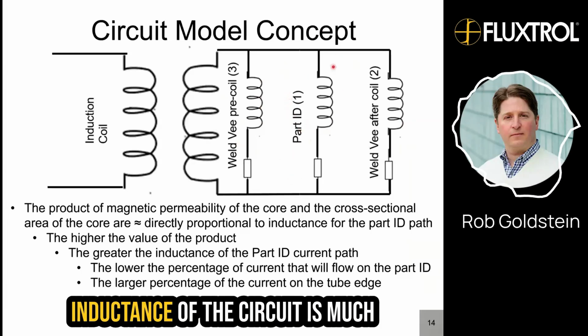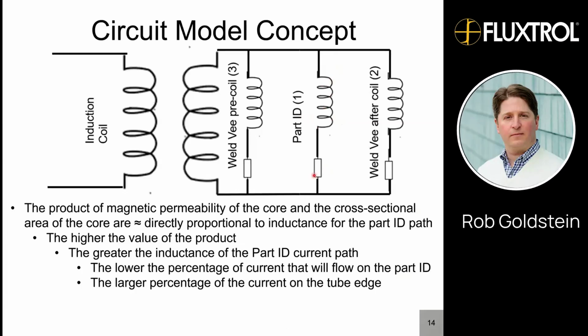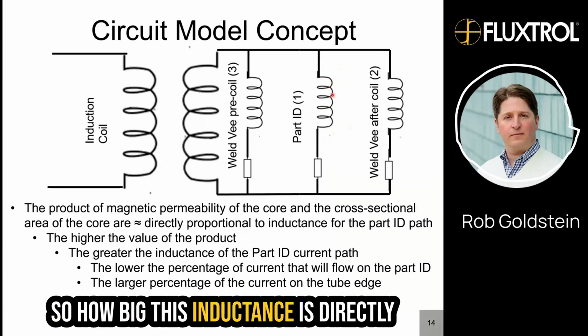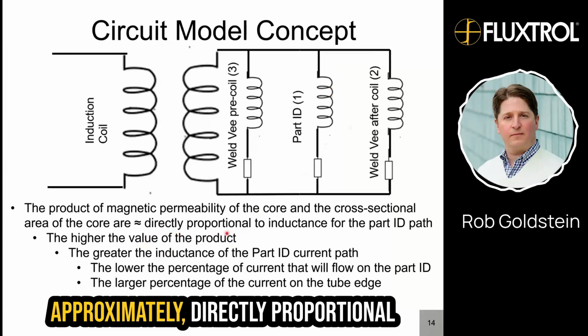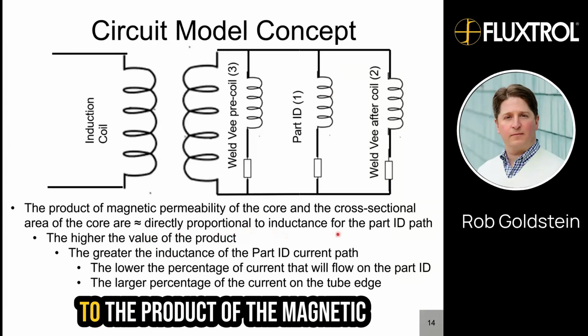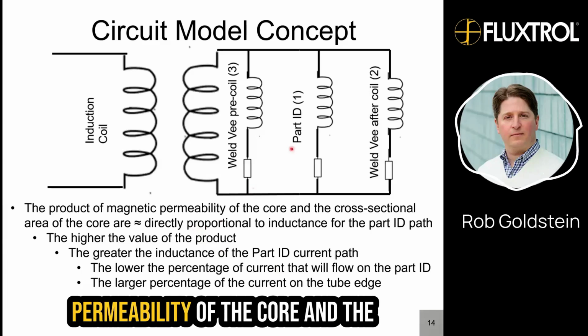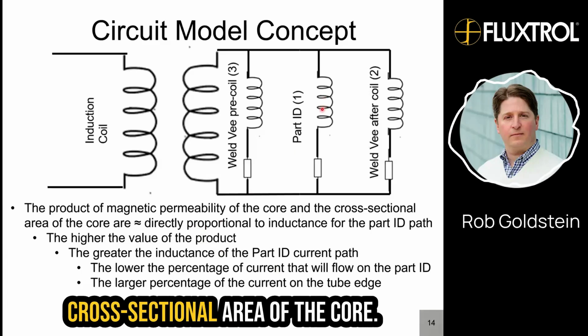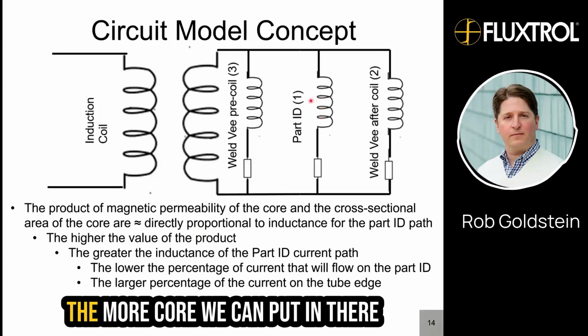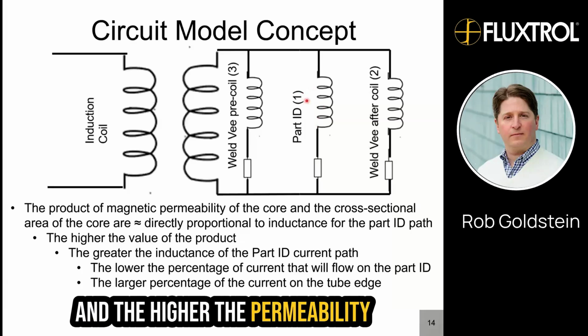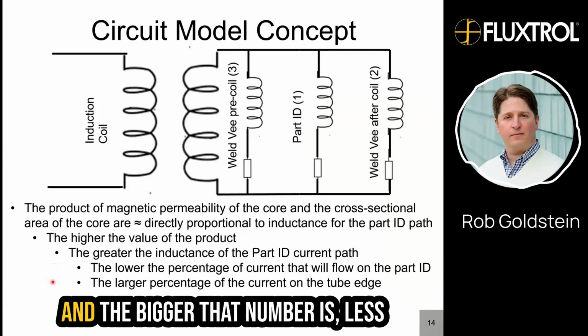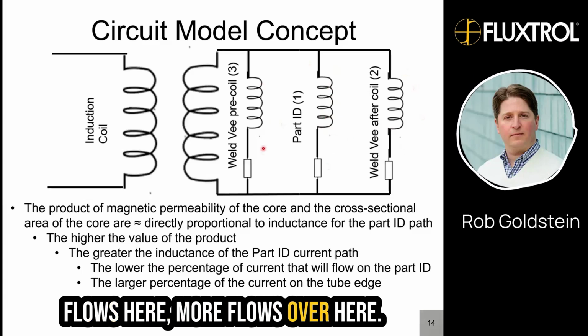And the inductance of the circuit is much larger than the resistance. How big this inductance is, is approximately directly proportional to the product of the magnetic permeability of the core and the cross-sectional area of the core. The more core we can put in there, and the higher the permeability, the bigger that number is, and the less flows here, the more flows over here.